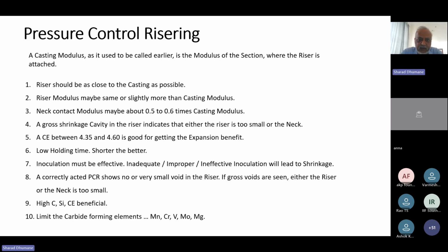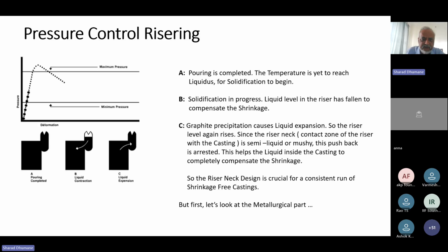Neck contact modulus may be about 0.5 to 0.6 times casting modulus. This is, I think, the most important point, that unlike in steel, where the neck modulus is 1.1 times casting modulus, if we give the same neck modulus in ductile iron, it will contribute to neck shrinkage. So here, when this is about to solidify and about to expand, if at the point of expansion this neck is not frozen, not solidified, then all that expansion will push the liquid metal into the riser.